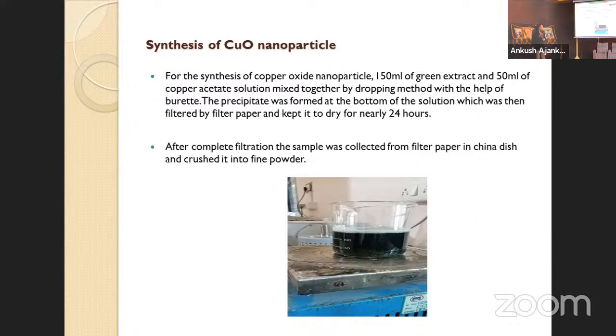Next, the main part of our project is synthesis of copper oxide nanoparticle. For this, we now have green extract and copper acetate solution. We have to take 150 ml of green extract and add 50 ml of copper acetate solution to it by the dropping method. After completion of the dropping, a precipitate forms inside the beaker, and we can see it forming and settling down at the bottom of the beaker.